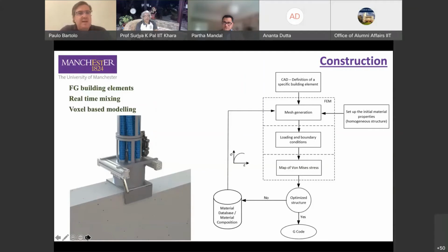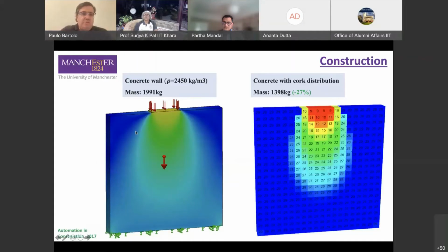We are also using expanded clay, but we are focusing more on cork because it's a very sustainable material with excellent thermal properties. And basically what we can do using this digital platform is illustrated here. So if we start with a construction element, we run a finite element simulation in order to identify areas where, due to the lower loading conditions, I can replace concrete by a mixture of concrete and cork. And this is the map of the building element optimized according to our software, where we have areas where concrete was replaced by a composition of concrete and around 30% of cork.